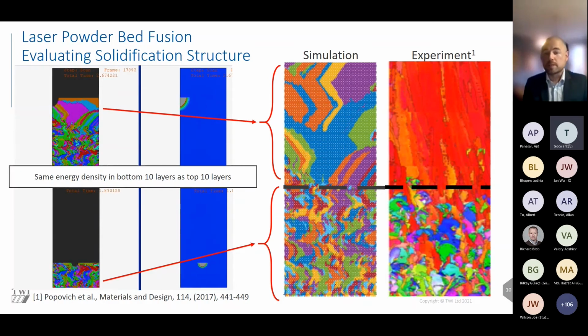And as Professor Toll was highlighting earlier, often we just do process parameter optimization on a nice tiny square section column or cube. And then we apply those parameter sets to something that's incredibly topology optimized and complex. And we shouldn't be surprised when that doesn't work out very well, because as heat builds up, it changes how the material is responding and solidifying in the transformation kinetics that take place.